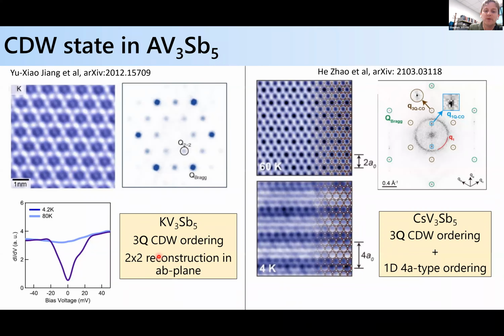These peaks are consistent with what they call a 2x2 reconstruction of the unit cell in the AB plane, which can then be modeled with this so-called 3Q charge density wave ordering, which is a known instability for a kagome lattice. Okay, and also in a tunneling spectrum collected below the transition, you can see there's this gap that opens. It's not a complete gap, it's a partial gap. So that's consistent with the optics data from earlier, although I'll note the magnitude of the gap seems to be different between the two probes.